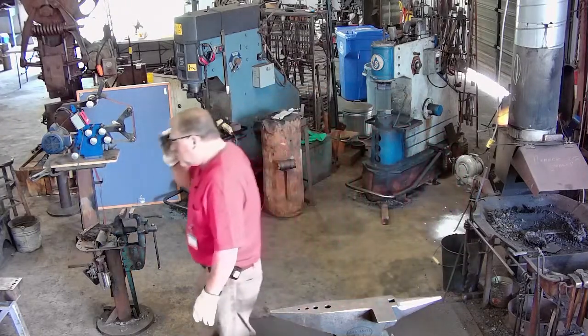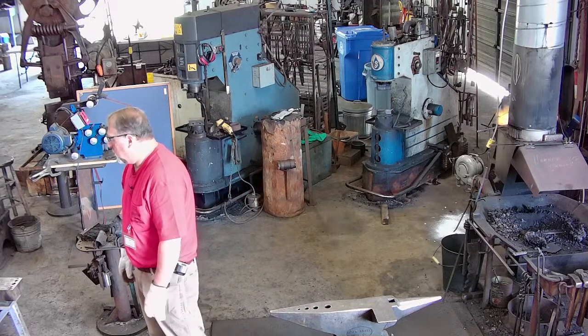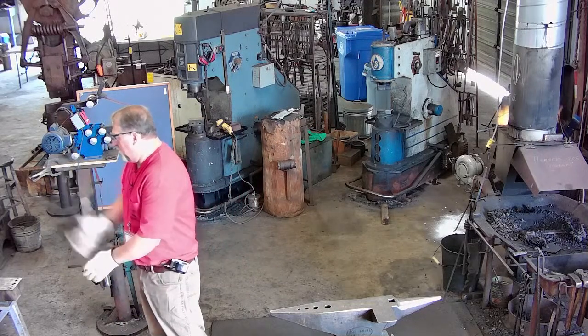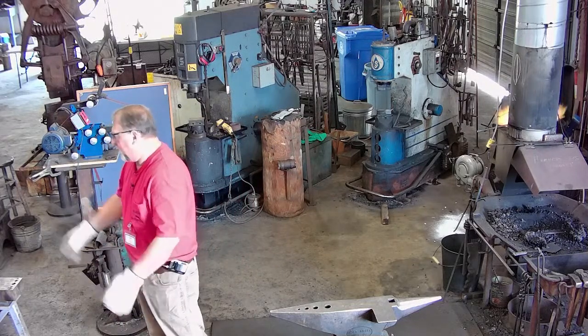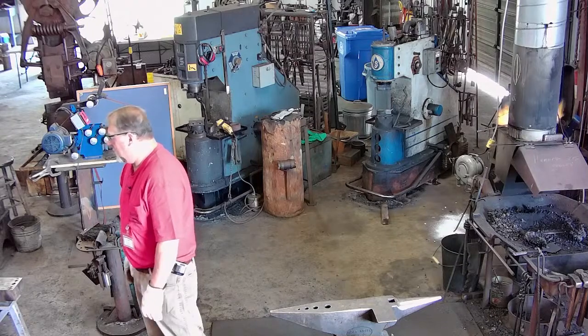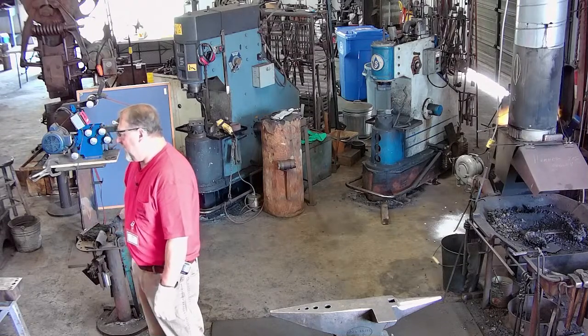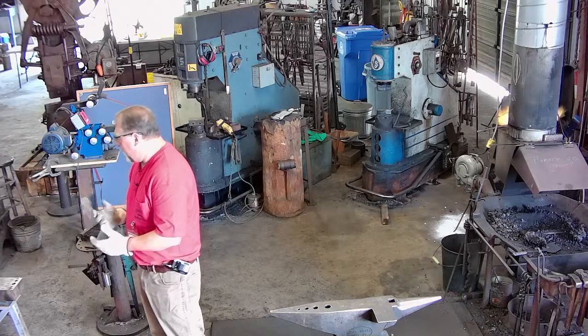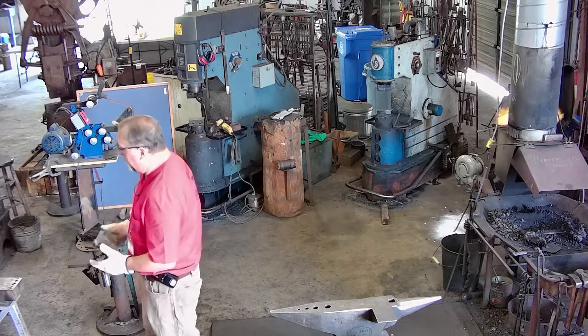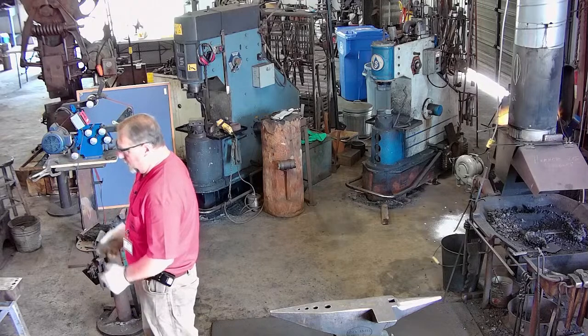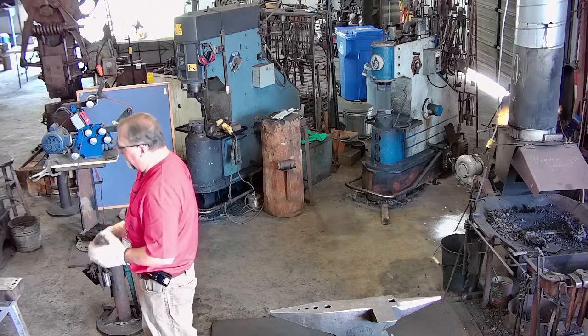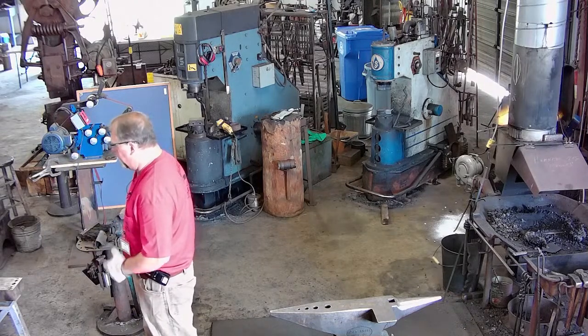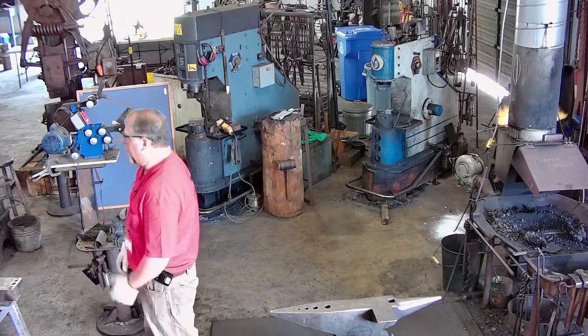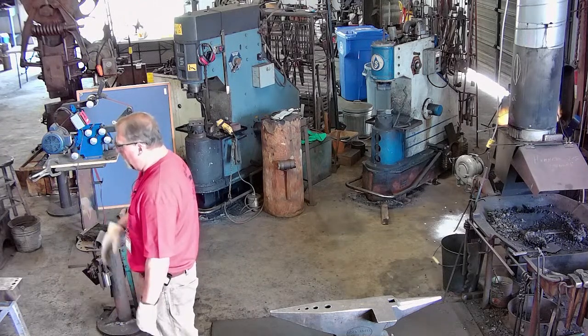If the layers start to separate, how do you correct that? I usually take a chisel, split them in half, and just modify whatever I'm making. You can't put plugs in there and redo it. If you try to fix a shear or a delam in the middle of a billet, there's a good chance it'll still be there and you'll find it in your final grinding. So if you screw up in the beginning, you'll just scrap it or modify what you're doing.